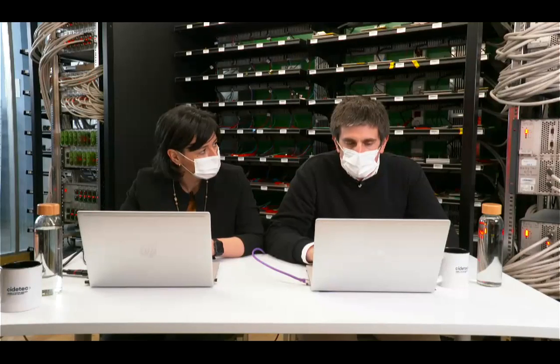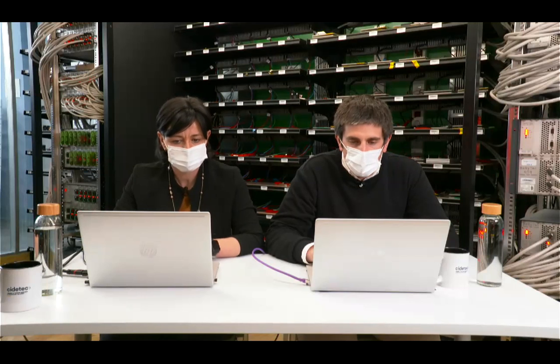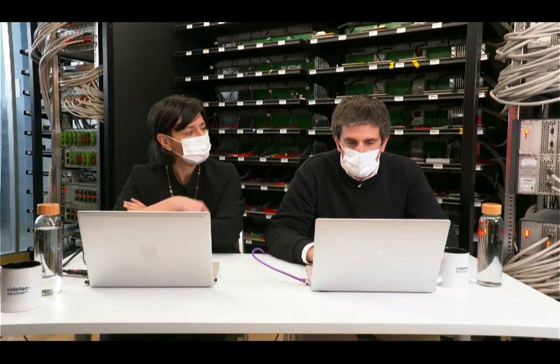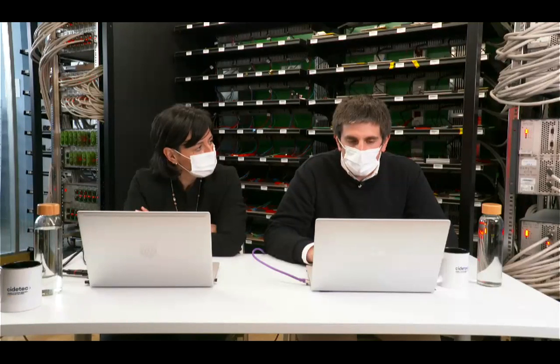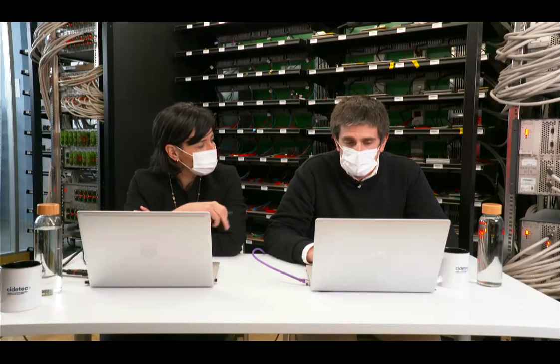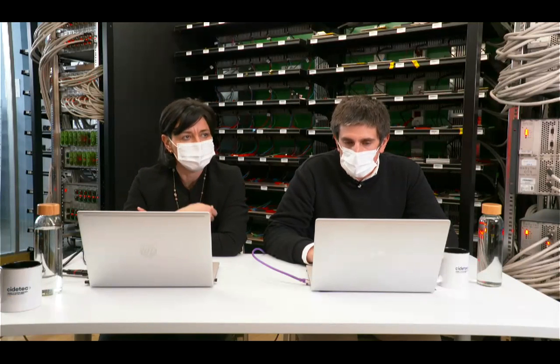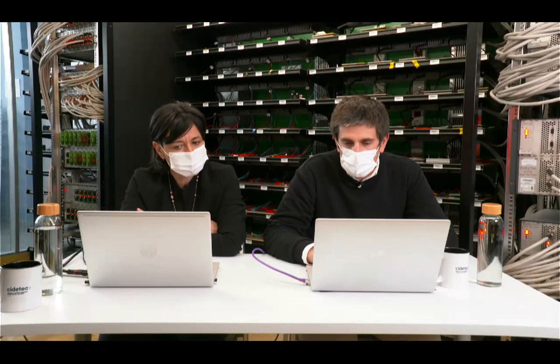Yeah, and another question regarding this calendaring process is that it depends on the cathode chemistry. And yes, of course, we need to optimize this because the density that you are targeting for NMC is different than for LFP. Of course, we are always trying to calendar the electrodes as much as possible, but they have to work. So in order to reach the target density that we want, for example with NMC, we need to adjust the pressure, and it's different than for LFP. There are some approximate values that we use, for example, 3.2 grams per cubic centimeter, which of course is a value that you cannot achieve with LFP. So it depends on this.